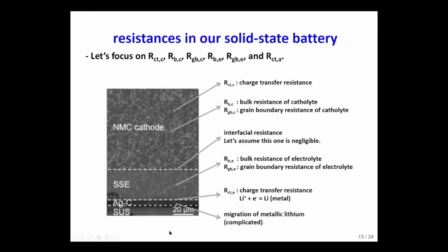If you look at the solid electrolyte layer, you can see that there are bulk and grain boundary resistances for the solid electrolyte. And we have to consider the charge transfer resistance at the anode. In this work, we focused on figuring out the influence of each resistance component as quantitatively as possible.